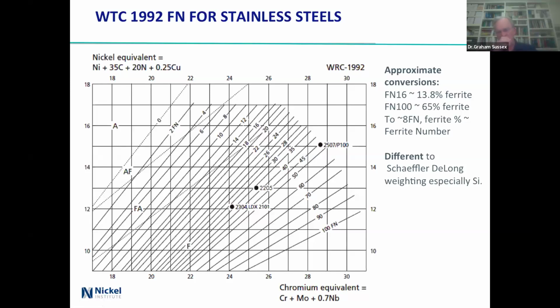So let's do some conversions. If you're looking for a ferrite number of 16, then that's about 13.8% ferrite. If it's 100, that's about 65% ferrite. And for very low ferrite numbers, up to about 8 ferrite number, the ferrite percentage is approximately the same. And here are the ferrite numbers across there.